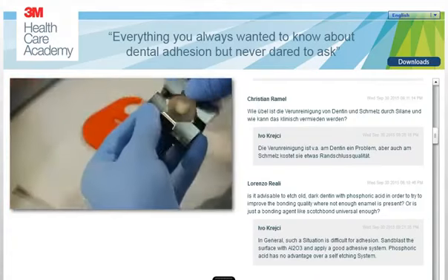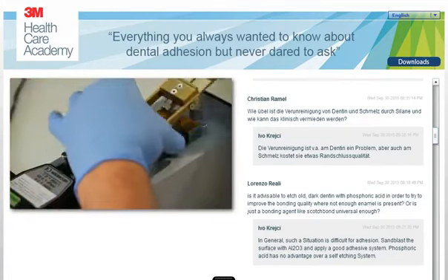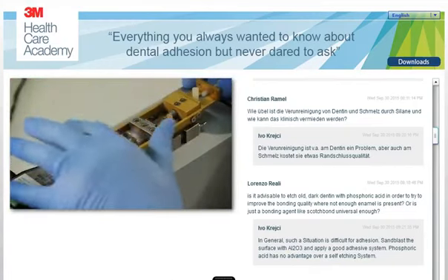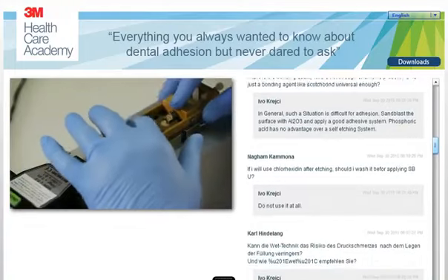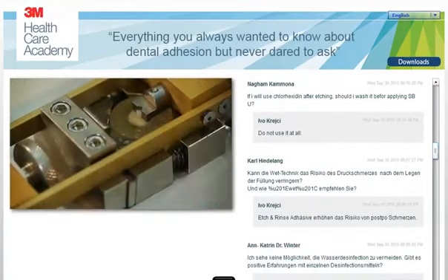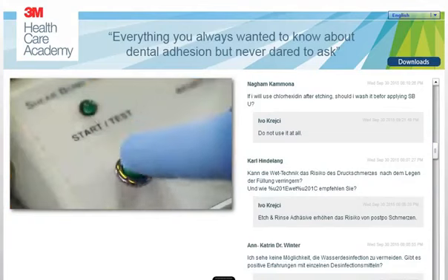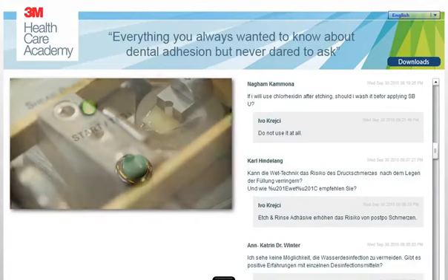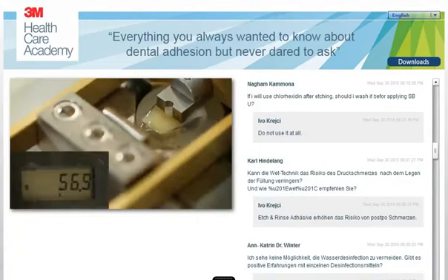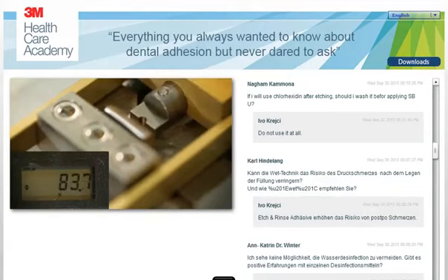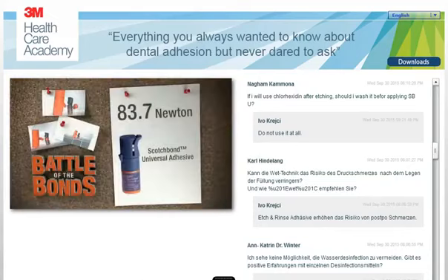Each sample was placed in a clamp and loaded into the portable shear bond strength testing unit. The wheel was slowly turned, bringing the shearing mechanism into contact with the composite. Once the Start Test button was pressed, the shearing force against the composite was gradually increased until the composite debonded. The force required to break or debond the samples was recorded in newtons on the electronic gauge. In this example, 83.7 Newton was the force needed to debond the composite using Scotch Bond Universal Adhesive.